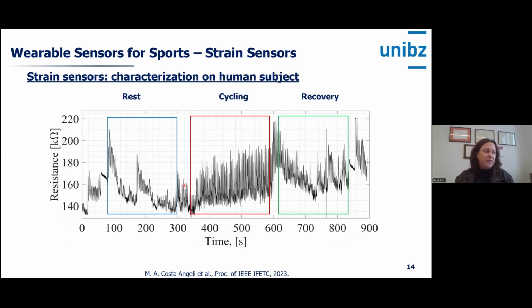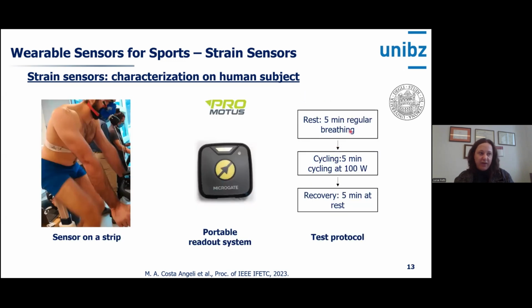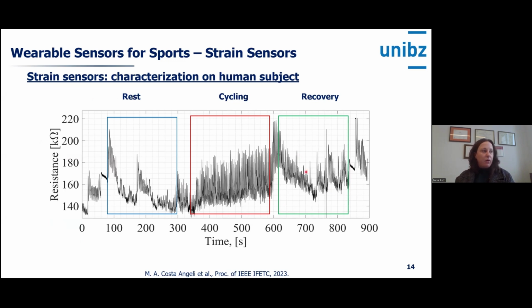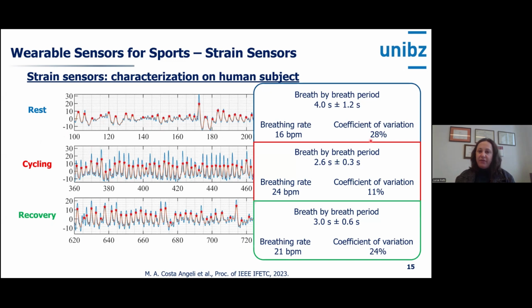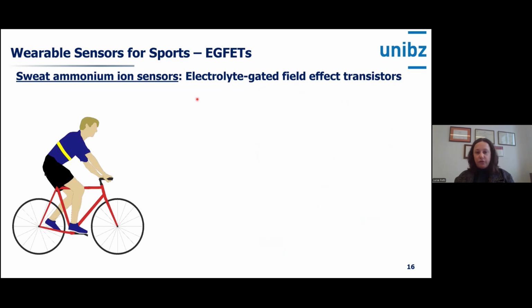What is interesting to see are the resistance changes. It's a simple resistive sensor with the different phases: resting, cycling. You see, we have this 5-minute protocol of resting, cycling, and recovering. From here on, we look at the extraction of the different parameters: the breath-by-breath period, the breathing rate, a coefficient of variation, and finding the patterns to be able to discriminate between those different phases. There is clearly still work to do on that.